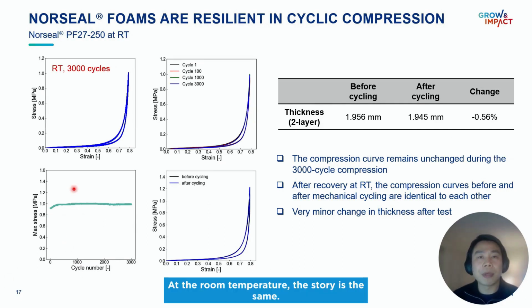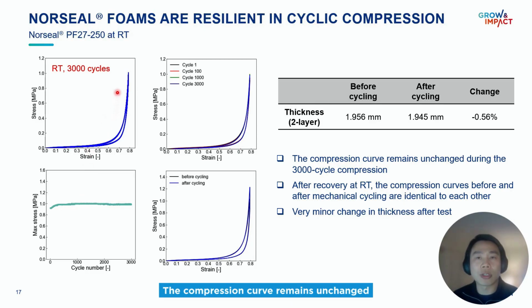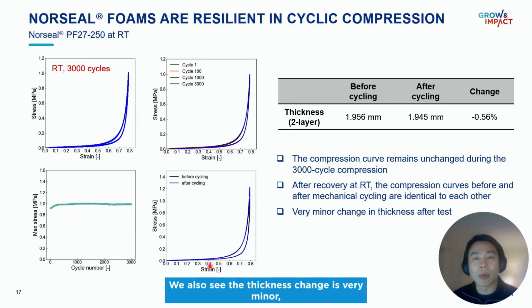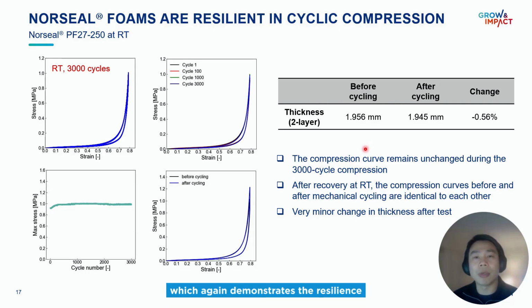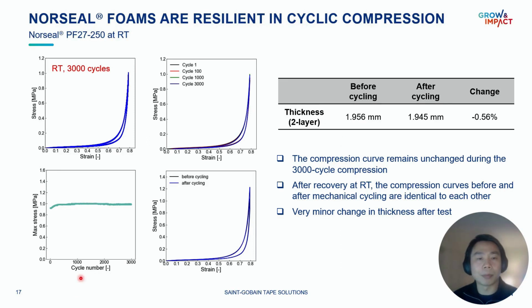At the room temperature, the story is the same. The compression curve remains unchanged through all 3000 cycles. The maximum stress remains constant, and the before and after 3000 cycles curve are again identical. We also see the thickness change is very minor, which again demonstrates the resilient properties of this material.